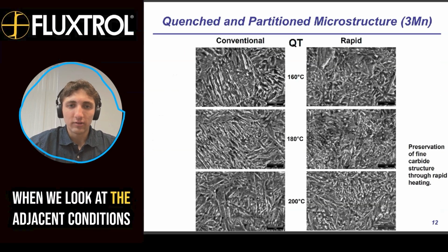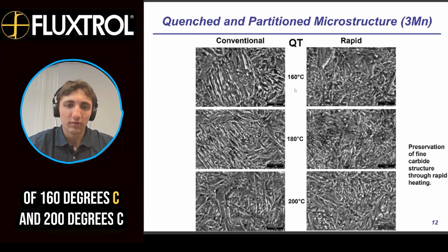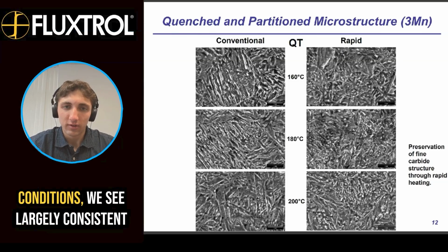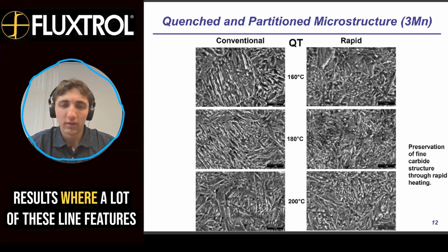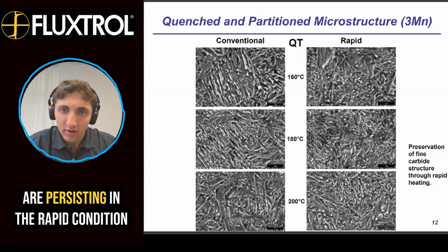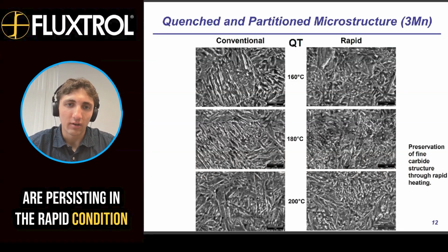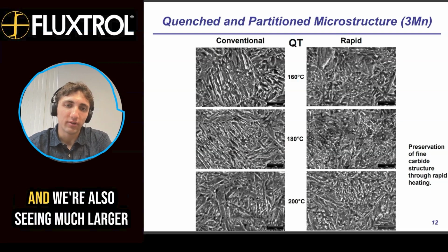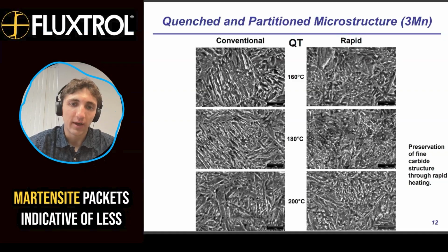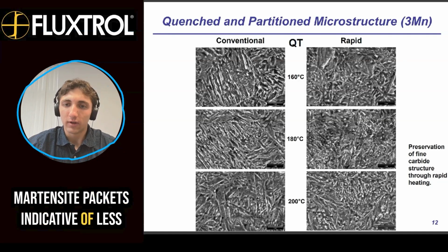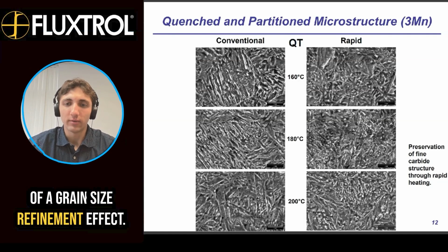When we look at the adjacent conditions, the 160 degrees C and 200 degrees C conditions, we see largely consistent results where a lot of these line features are persisting in the rapid condition and not so much in the conventional. And we're also seeing much larger martensite packets, indicative of less of a grain size refinement effect.